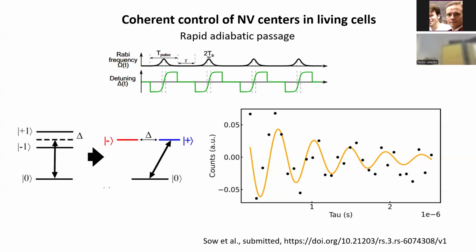Back to the temperature sensing, I just wanted to ask, is there any effect of local heating when we are optically trying to measure? There is an effect indeed. It's also a very important kind of artifact. We have calibrated this. We need to avoid heating above 0.1 degree, at least for the cells that we were working with. We need to keep our laser power below 10 microwatt.